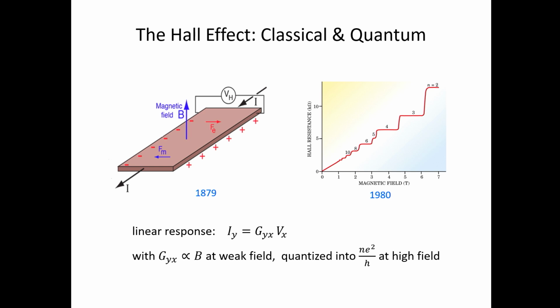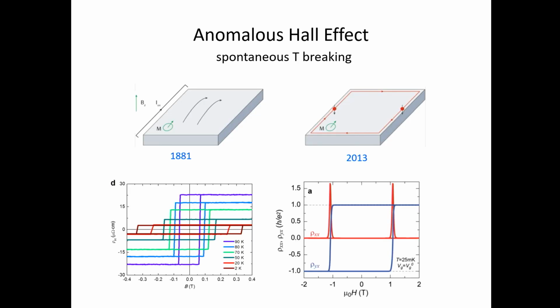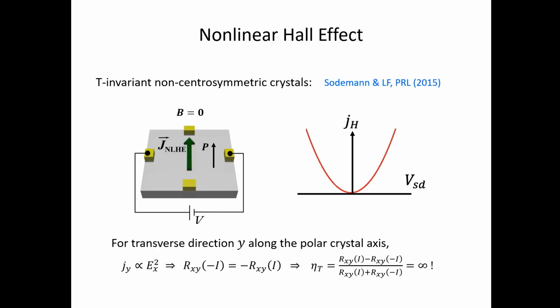However, in the 80s, it was found that if you increase the magnetic field and work with semiconductors, this Hall conductance can actually be quantized into some integer multiple of e squared over h. This is called the quantum Hall effect. Now, without an external field, the material itself can spontaneously break time reversal symmetry. These are magnetic materials, and they can also exhibit the anomalous Hall effect, the zero field Hall effect. In conductors, this was observed a long time ago, and about 12 years ago, this anomalous Hall effect was found to be quantized in magnetically doped topological insulator films, and this is similar to the quantum Hall effect, but now without external field.